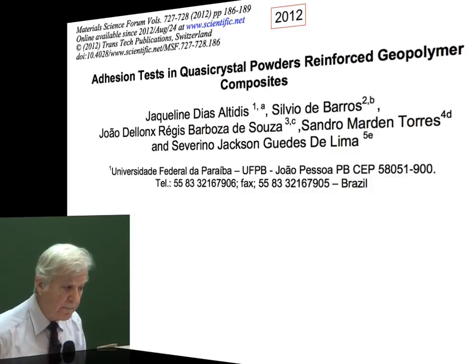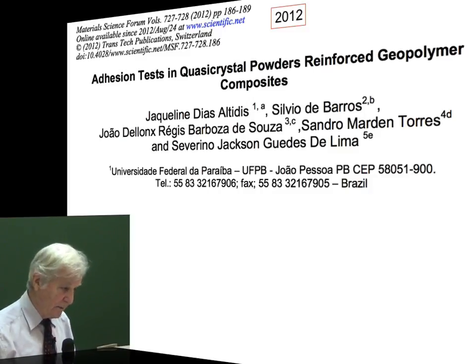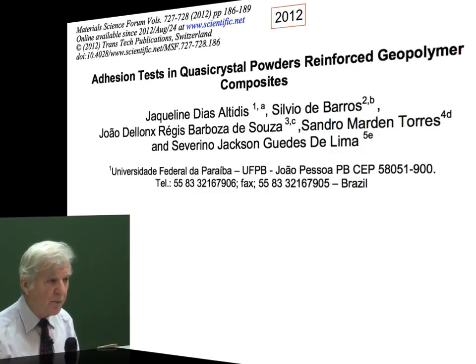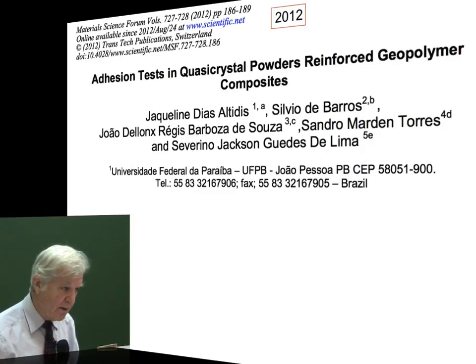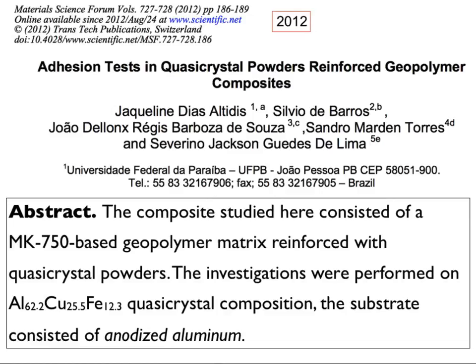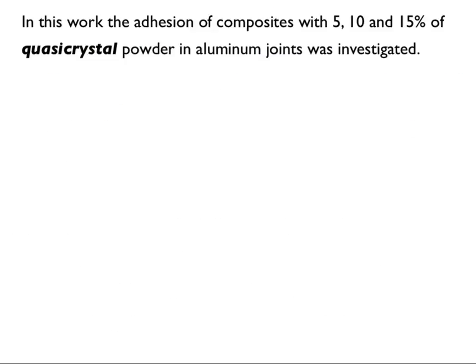Continuing with the adhesion on metal, the same group studied something very strange. Adhesion tests in quasi-crystals powders reinforced geopolymer composite. But this time they studied it to increase the adhesion on aluminum. The composite studied here consisted of a metakaolin-based geopolymer matrix reinforced with quasi-crystal powders. The investigation were performed on Al62.2Cu25.5Fe12.3 quasicrystal composition, and the substrate consisted of anodized aluminum. In this work, the adhesion of the composite